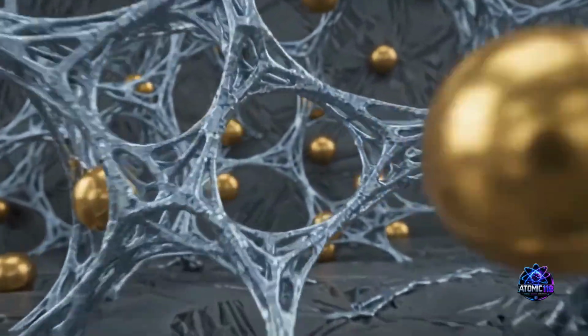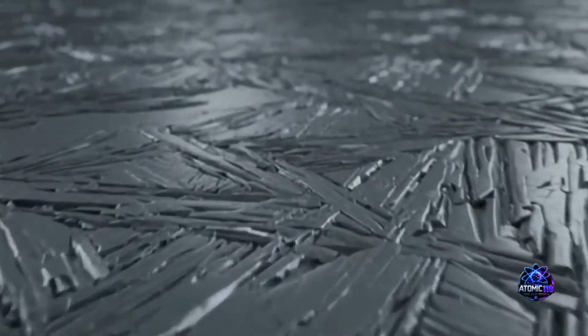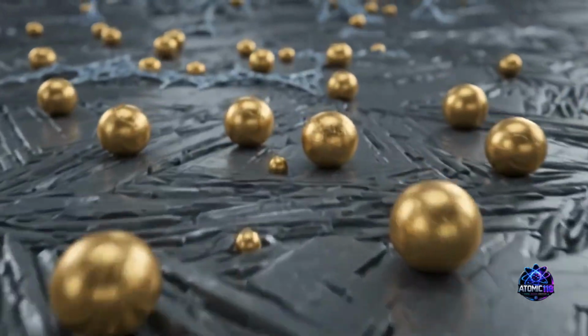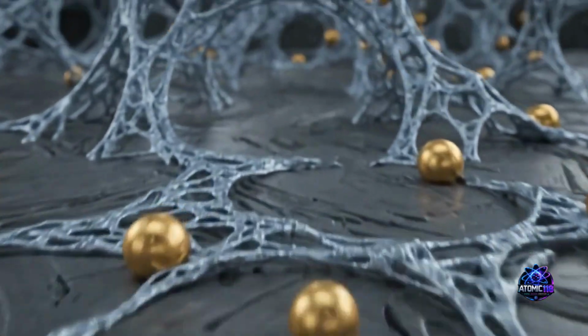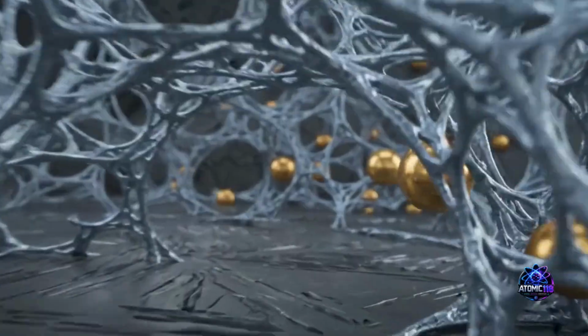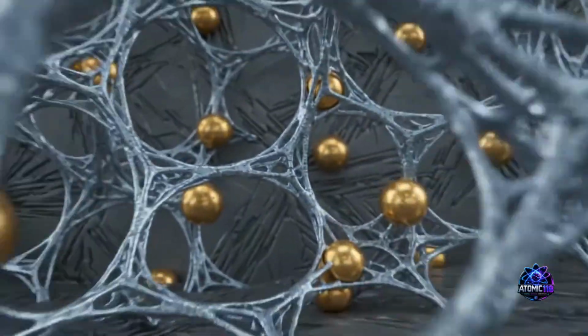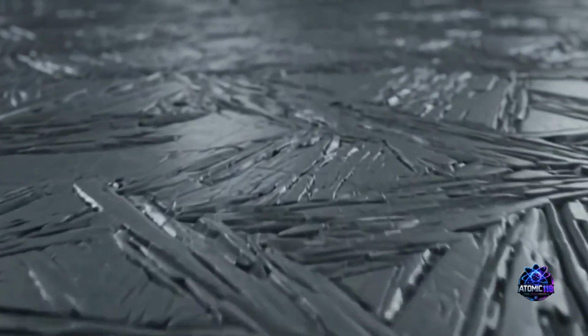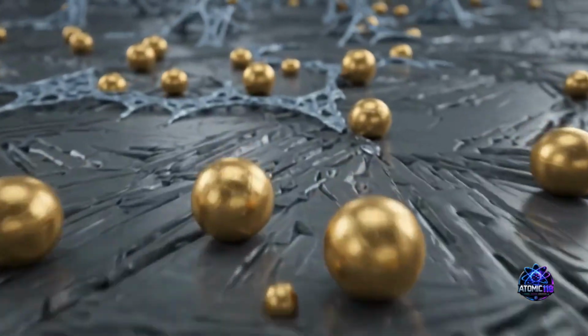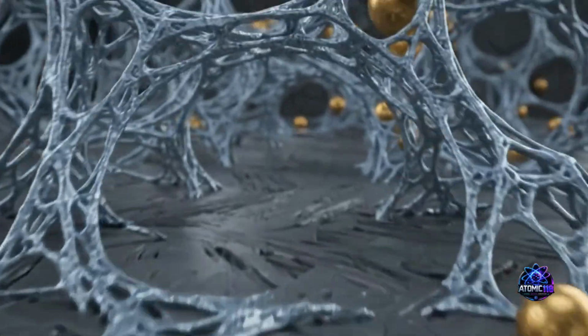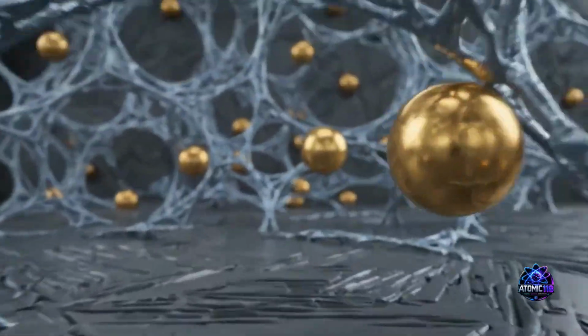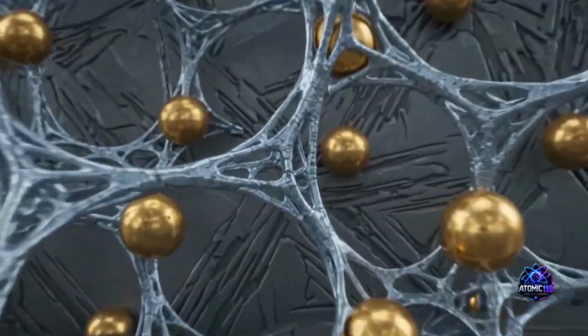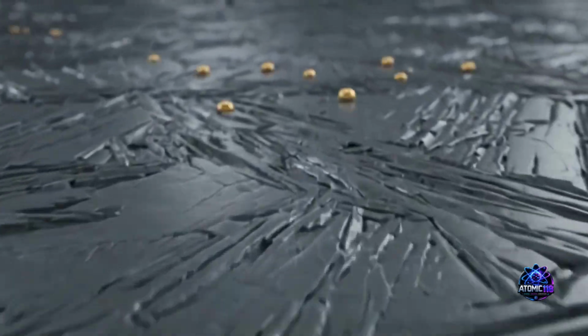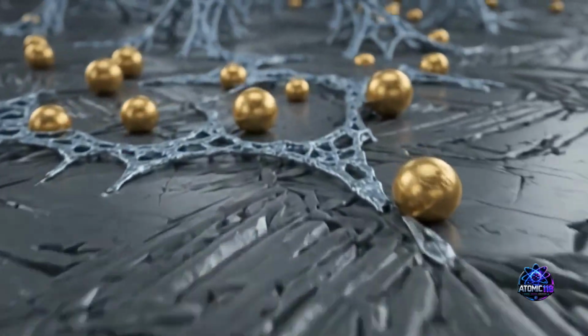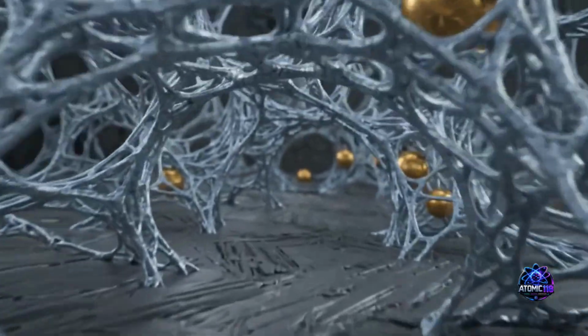Wow. And molybdenum. With its massive cohesive energy and perfect orbital overlap, it must build something far more complex than a simple 1-to-1 ratio. It builds an M6C carbide. This is a massive, complex molecule where 6 metal atoms, usually a mix of molybdenum and iron, trap a single carbon atom. 6-to-1. Yeah, so instead of a tight, dense little crystal like vanadium, molybdenum creates this heavy, immovable molecular anchor within the steel lattice.